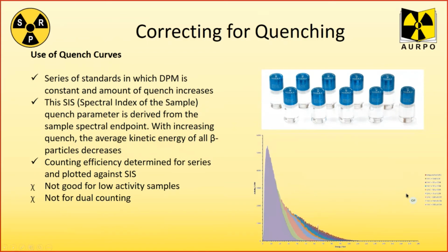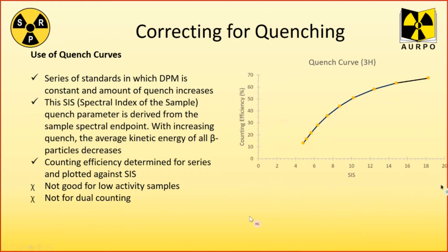Other methods to correct for quenching involve the generation of quench curves. A series of standards, as shown here, in which the DPM is constant and the amount of quenching increases, can be used. The quench indication parameter, SIS, or spectral index of the sample, is derived from the sample spectral endpoint. As I already mentioned and shown here, with increasing quench, the average kinetic energy of the beta particle decreases. The counting efficiency is then determined for the series and plotted against this SIS parameter. Samples with unknown quench can then be measured and the value of SIS given by the counter.